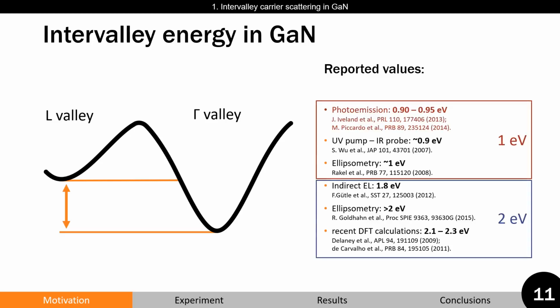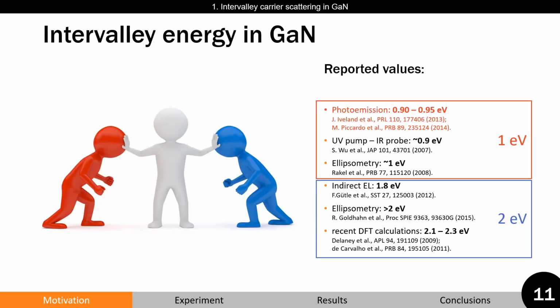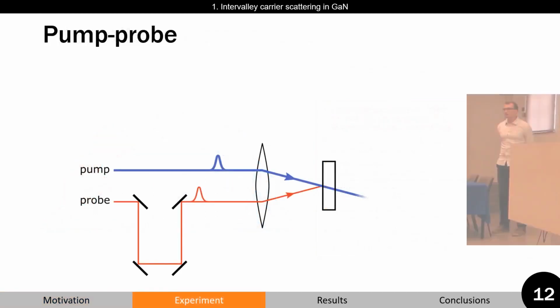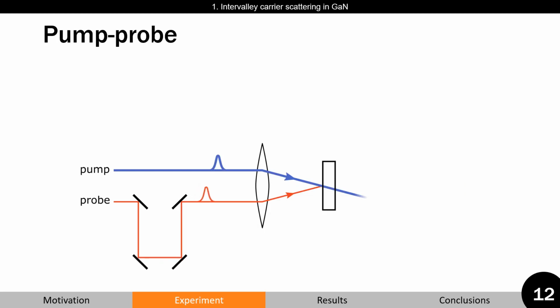Recent photoemission measurements reignited conversation between different groups. Therefore, we decided to revisit this value by conducting an independent measurement. We chose to use pump-probe spectroscopy, which is a measurement technique used to study ultrafast carrier dynamics. In this measurement, the laser pulse is split into two parts. The stronger pump is used to induce non-equilibrium states in the sample, while the weaker one, the probe, is used to study pump-induced changes. By changing the travel distance of the probe pulse, optical constants can be measured as a function of time.